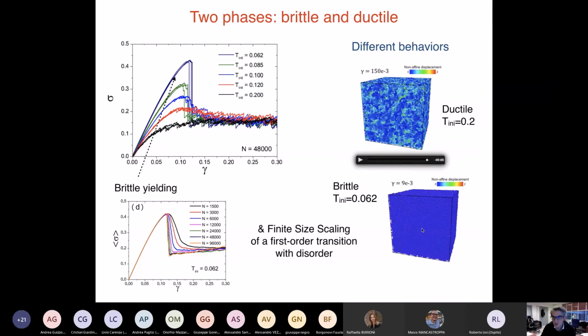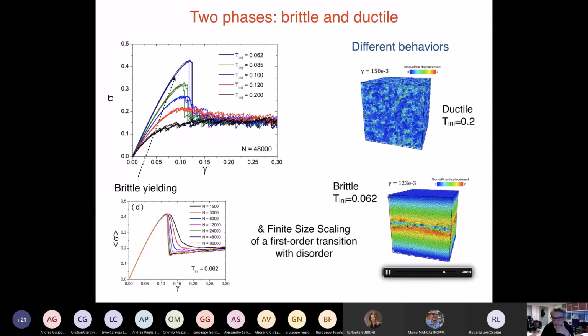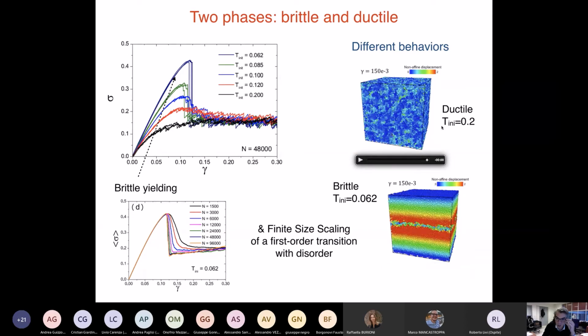So it's not an abrupt failure. And instead here, when the system is brittle, which corresponds to this, what you're seeing is how the system behaves in this case. So what you see, nothing happens, so there is no plastic behavior. And then at a certain point, bang, there is a shear band in the middle of the system, at least in this sample, and which corresponds really to this discontinuous jump that you see here. So you really see that the two different behaviors that we see in a macroscopic way in the stress versus strain curve correspond to two extremely different microscopic ways of failure. This we will call ductile, and this we call brittle.